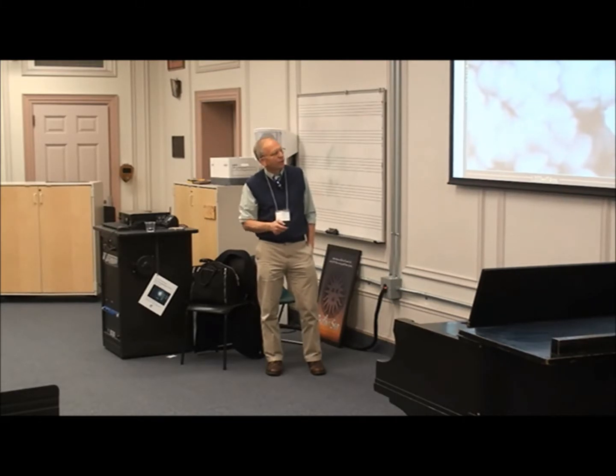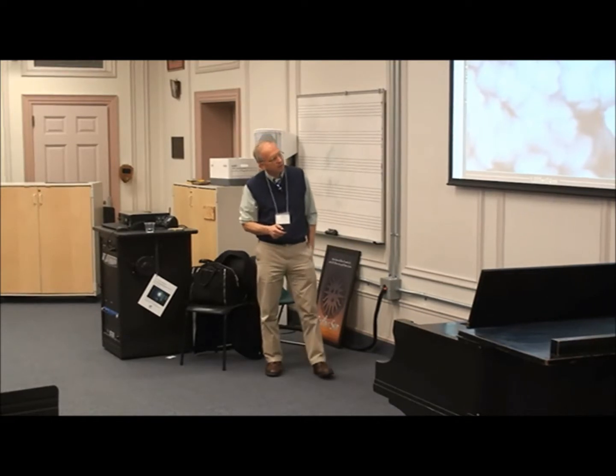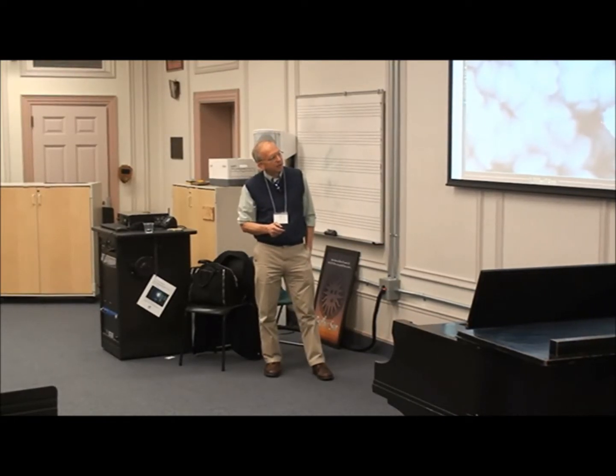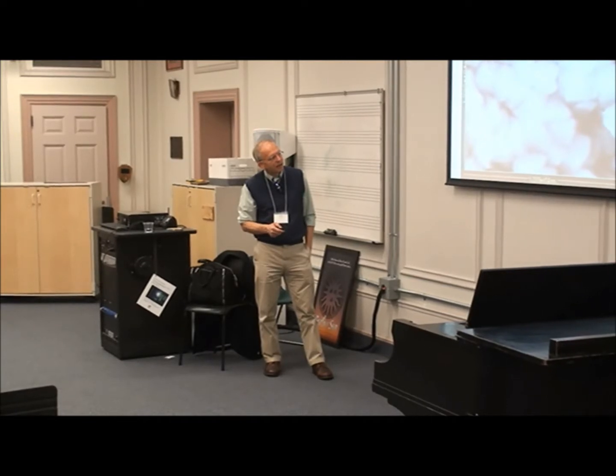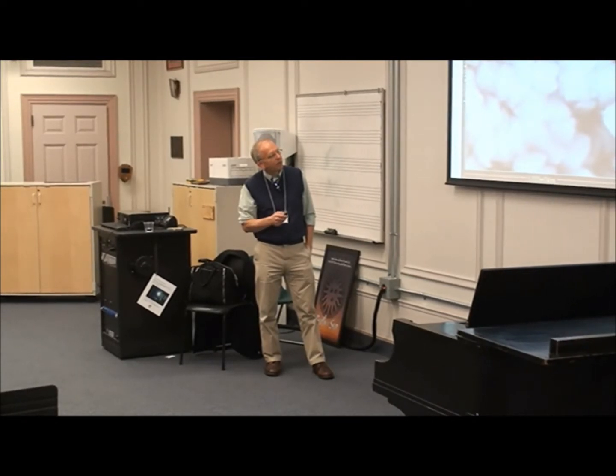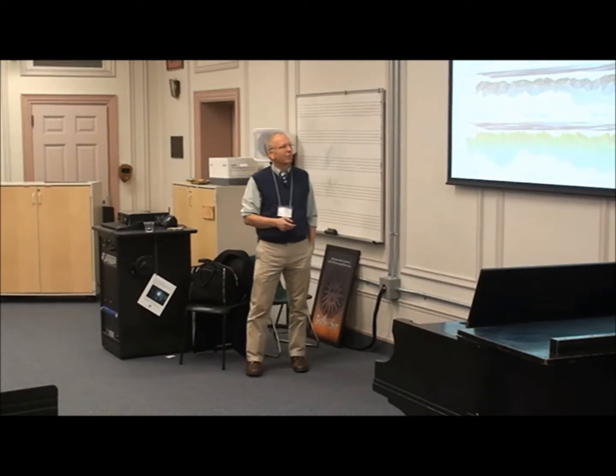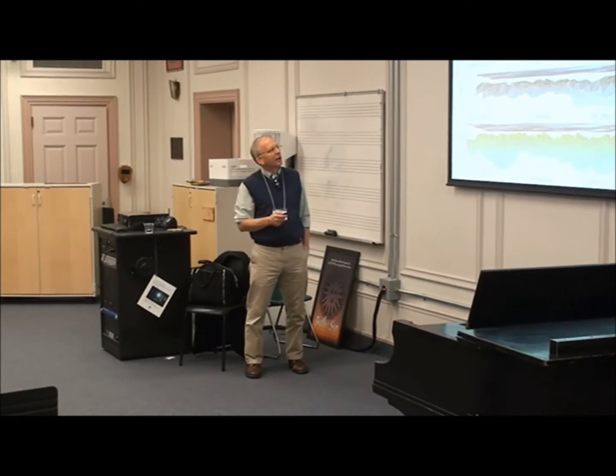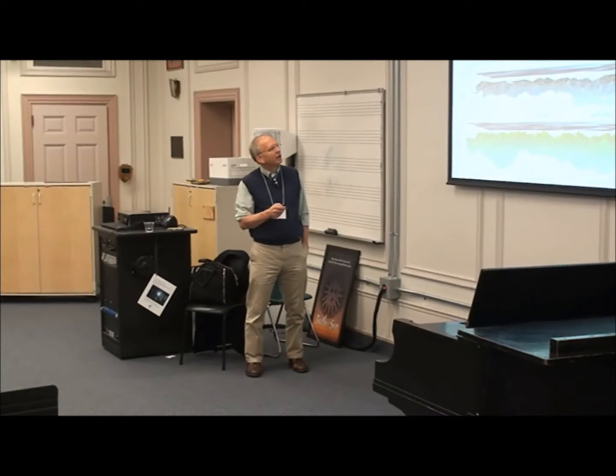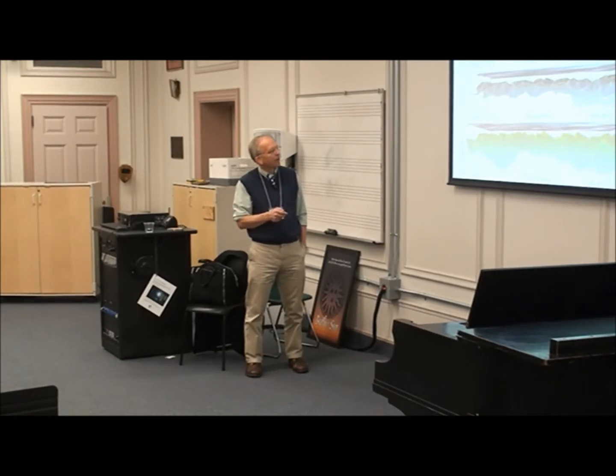We also see, and this is a very old thing, it's now like 23 years old, this measurement. I know because I got this the first year I was at WPI, and that was 23 years ago. But look at this edge here. You can see the scanning lines here. But at the time it was very good, but you know, we can do a lot better than that, I'm sure. So anyway, the idea now is we used the line segment before, and now we're going to use a triangle. And so we tile in this way using triangles, and the triangles get smaller and smaller. So we start off a little above 5 square micrometers, and we end up at 4,000 square nanometers.